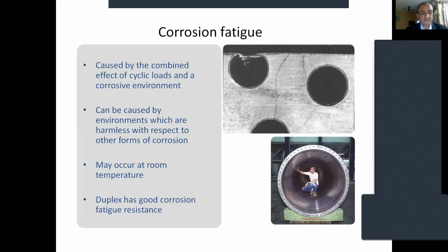Corrosion fatigue: it is well known that a material subject to a cyclic load can fail at a load far below the ultimate tensile stress of the material. If the material is simultaneously exposed to a corrosive environment, then failure may take place even at a lower load and after shorter times. So it's caused by the combined effect of cyclic load and corrosive environment, can be caused by environments which are harmless with respect to other forms of corrosion, and may occur at room temperature. Duplex, another form of stainless steel, has good corrosion fatigue resistance properties.